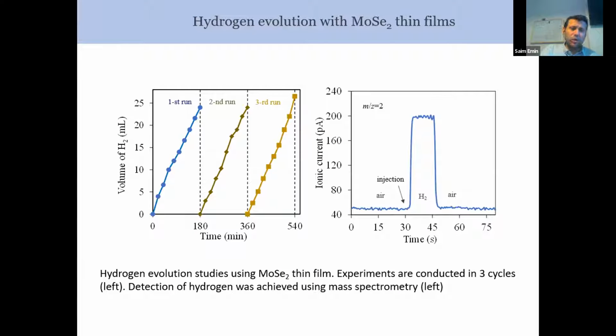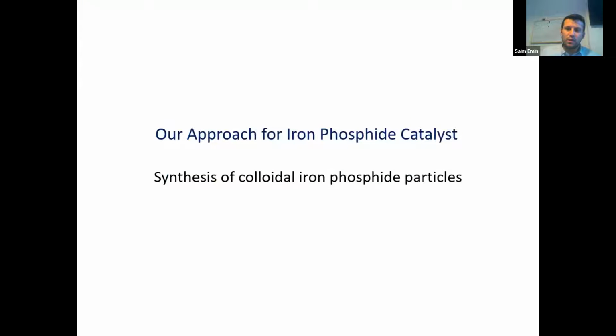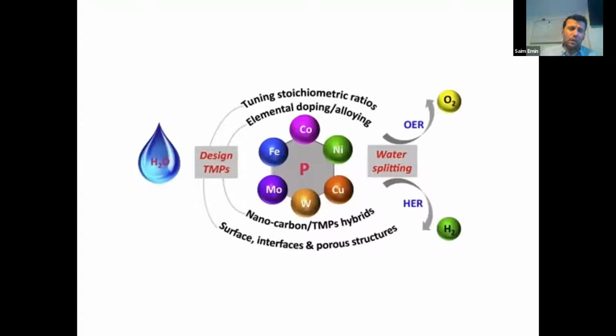We collected the hydrogen, and we saw that it is repeatable. It doesn't lose activity. Hydrogen was detected using mass spectrometry, and at the injection point at 30 seconds, we injected with a syringe the gas which we collected, and we have a sudden increase in the current. After we took out the syringe, when the mass spectrometer head is exposed to air, it drops again. So we can prove in this way that we generate hydrogen.